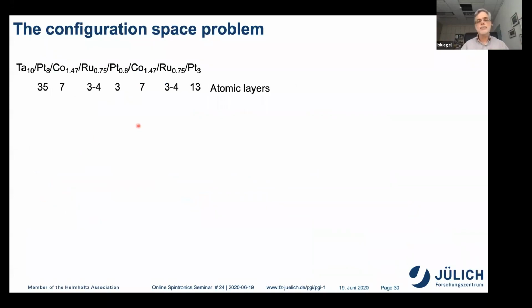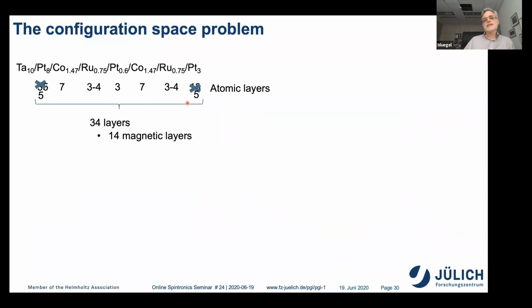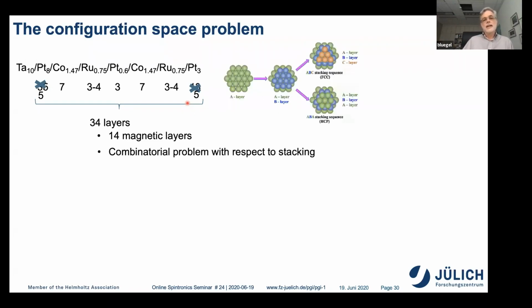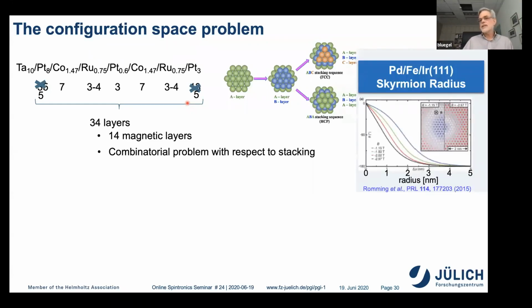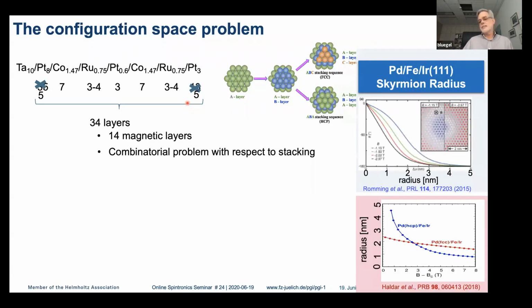Okay, when you work together with experimentalists, the experimentalists have great samples. So they have tantalum, platinum, cobalt, ruthenium, platinum, cobalt, ruthenium, platinum, and so on. And if you count up the number of atomic relevant layers, it's easily 40, 50 layers. And to calculate this is a little bit too much. And therefore, we have to reduce the complexity a little bit. Instead of these 35 layers here and these 13 layers here, maybe we reduce it to 5. Then there are still 34 layers. 14 of them are magnetic layers. And then you have a small combinatorial problem with respect to the stacking, because experiments have shown there is a big difference whether you have an HCP stacking or an FCC stacking.